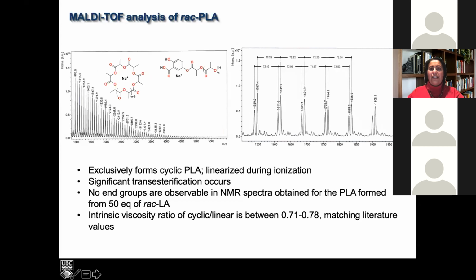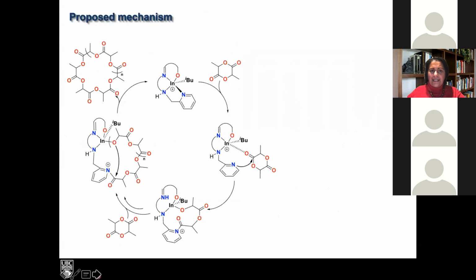I talked to my colleague in chemical engineering about such high molecular weight cyclic polymers. He was very excited to look at their rheology, etc. And what we think is happening with the pyridyl system is that the pyridyl arm is actually behaving as a nucleophile. It can initiate the polymerization, and once you initiate it, then you have an alkoxide, which is a much better initiator. It can keep on adding monomer until, for a lot of these, the point where they run out of monomer. This alkoxide will then attack the last carbonyl group because it's the most reactive, leading to chain termination but formation of a cyclic chain. And this is a cyclic chain that is relatively low in dispersity and really high in molecular weight.